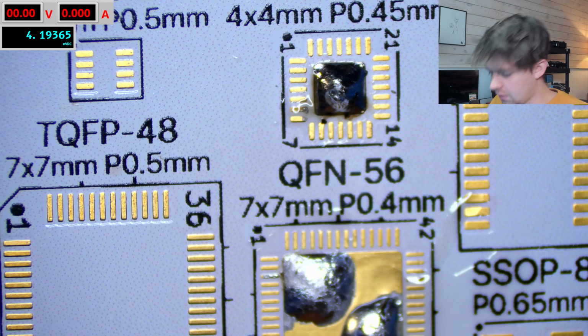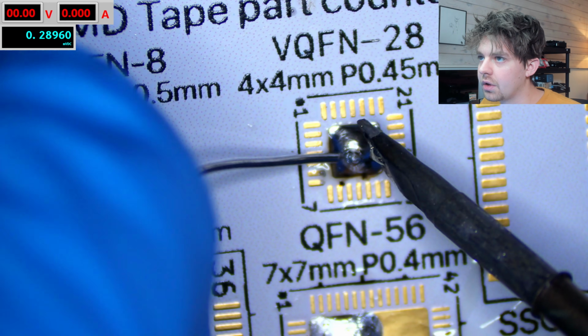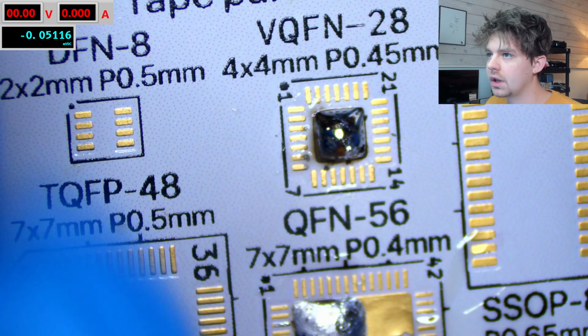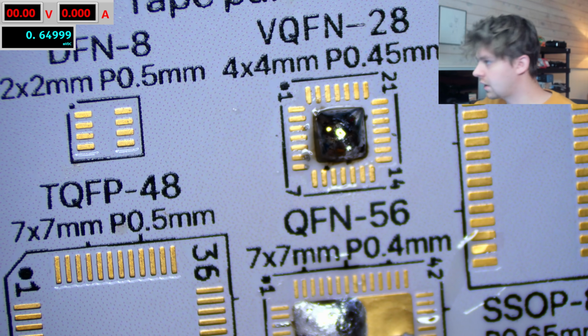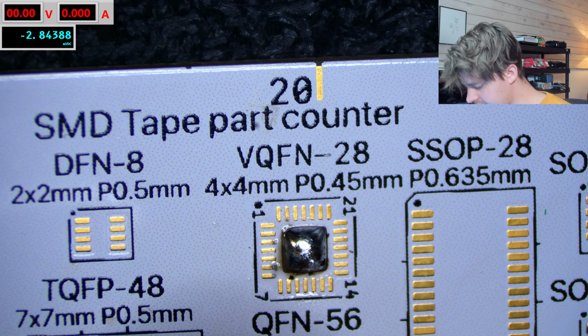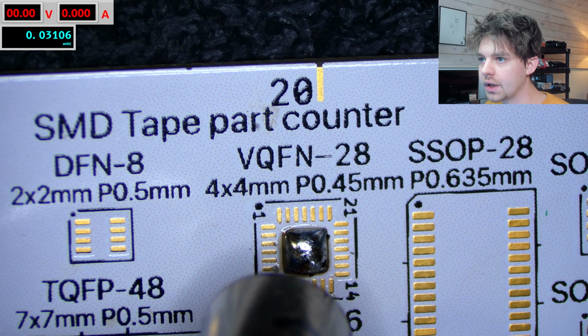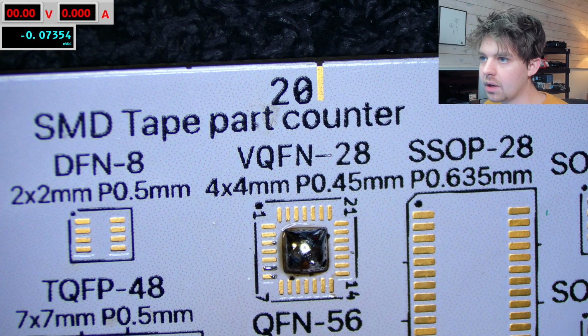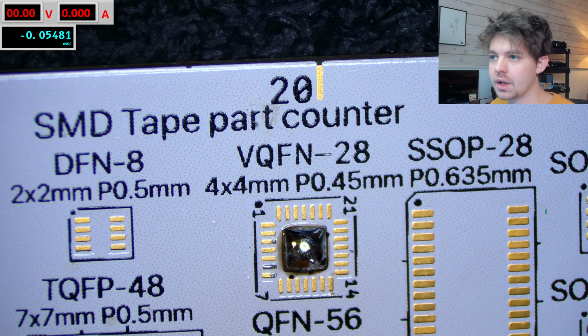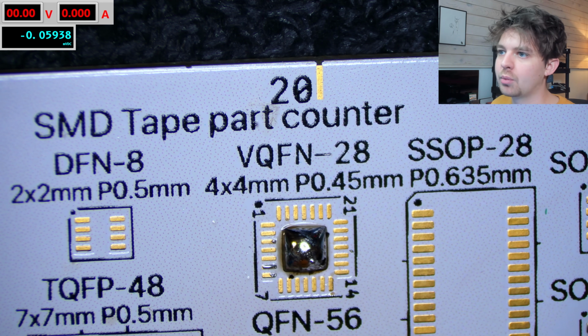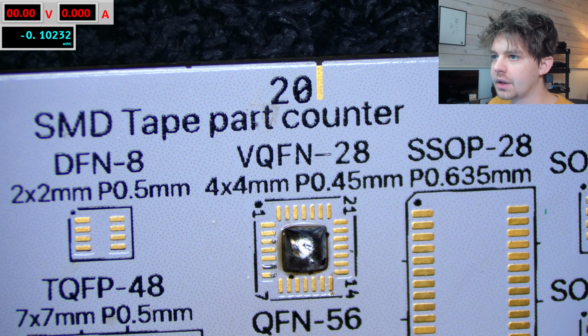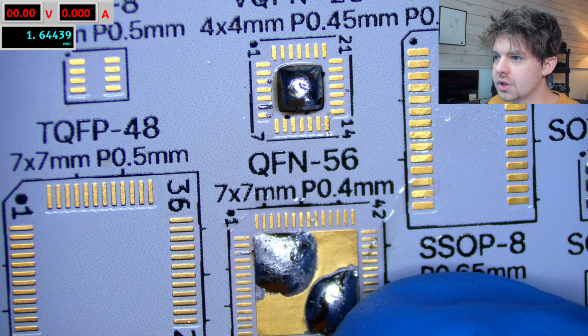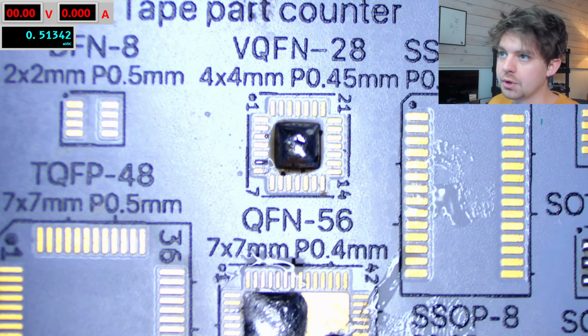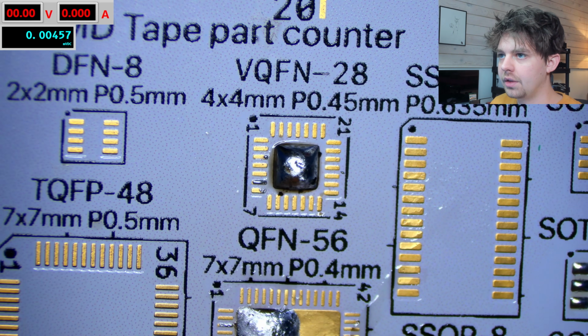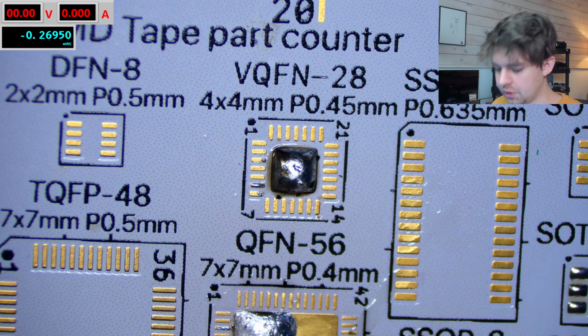So there's the silver solder. Obviously, you can see there's not a lot of flux core there, so we're not really getting a shiny joint to begin with because there's not a lot of flux. But there it is. Let's reflow this and see how it looks after it gets reflowed. So that's nice and melted now, and I'm just going to let go and let it solidify, and we'll see if it's more like the non-eutectic or more like the eutectic. So I would say this is actually more similar to the eutectic than the non-eutectic, which makes sense based on the plastic range being only 1 degree Celsius.